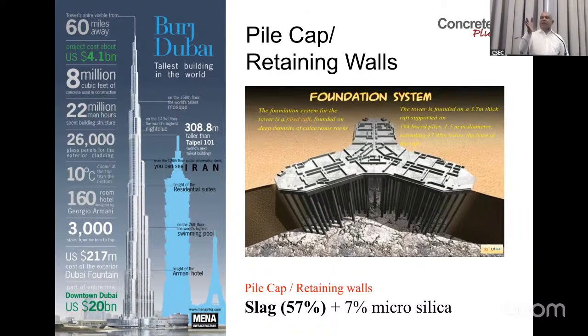One thing is, workability is not a critical issue because it's a very big area. Pile caps are quite big, so you can go for it and density. Of course, durability is there, especially for durability, you can go with either fly ash or slag, and always with microsilica to get the strength plus durability combination. They always go with 7% microsilica most of the time, 5 to 10%. This time they have used slag. So why did they use 57%?